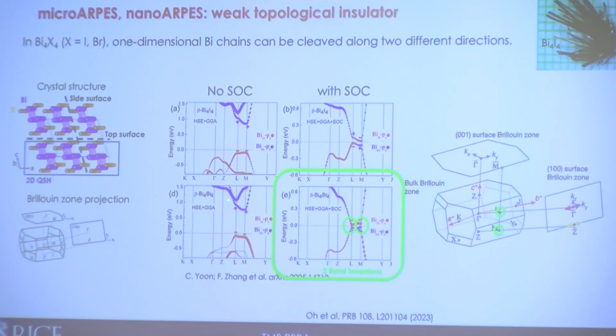But imagine this is a different case, where you just slightly tune this band gap. You can actually eventually end up with two band inversions here at the L point and N point. And what this means is that when you project to the top surface, these two sort of annihilate each other, so you get no topological surface states on the 001 surface, and then you get two Dirac cones on the side surface. So this would be classified as a weak TI. So it's actually important to experimentally figure out which of these two cases it is.